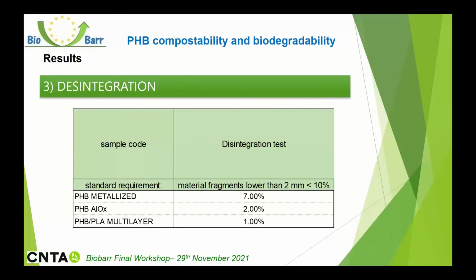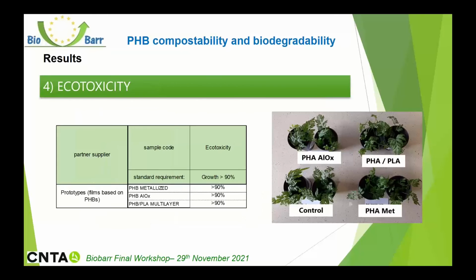Therefore, we tested the compostability assay with these 3 prototypes, and this disintegration test showed that the 3 ones were able to be compostable in 6 months approximately. The important thing we want to observe in this activity is whether the samples had the ability to disintegrate. And finally, these 3 last prototypes passed the ecotoxicity test. The 3 final prototypes passed the criteria.